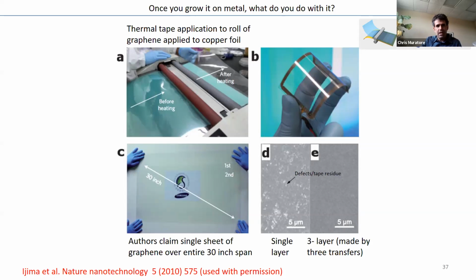So thermal tape is another tool that's used for transfer. It's sticky at one temperature and not sticky at a different temperature. So you can go either way. You can make it sticky when it's hot or not sticky when it's hot. And being able to turn off and on its ability to stick, it's a variation of what we talked about with the strain rate of those polymer stamps. So you can take the tape, stick it onto the surface, get transfer from the one surface and apply it to another by turning off the stickiness of the tape.